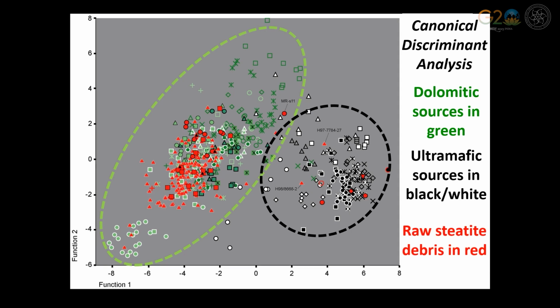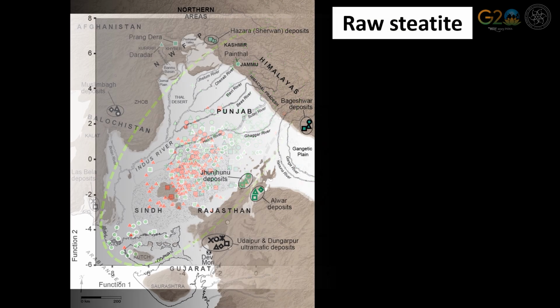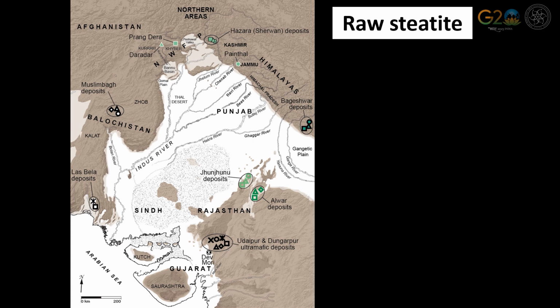When the data points for the raw steatite artifacts are superimposed, it is immediately clear that the large majority of them cluster with geologic samples of dolomitic origin. Only a handful of artifacts fall with ultramafic sources. After further iterations of comparison, which I will not show here due to time constraints, we were able to assign artifacts to discrete sources, or at the very least, to individual regions. So, with this geologic provenience data now in hand, we can provisionally reconstruct steatite acquisition networks during the Indus period.